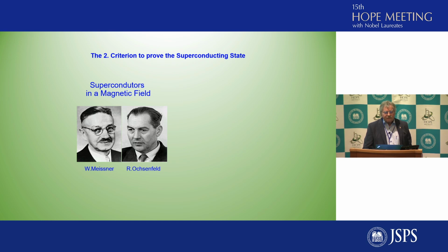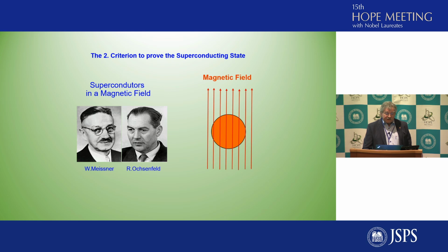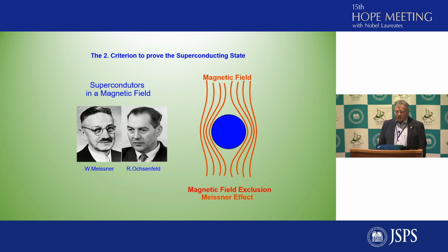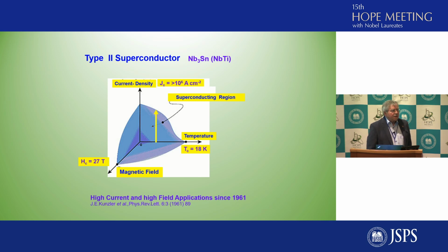So the second criterion to prove superconducting state is the Meissner effect, the effect that a magnetic field which at high temperatures is penetrating the conductor, and below the critical temperature, the magnetic field is expelled. But still, these were not usable properties till the early 60s, when a second type of superconductivity was discovered, named in niobium-3 tin or niobium titanium. So this brought us to superconductors which were able to carry very, very high currents at low temperatures, greater than 10 to the 6 amps per square centimeter. That's 1,000 times higher than we are used to have in copper.